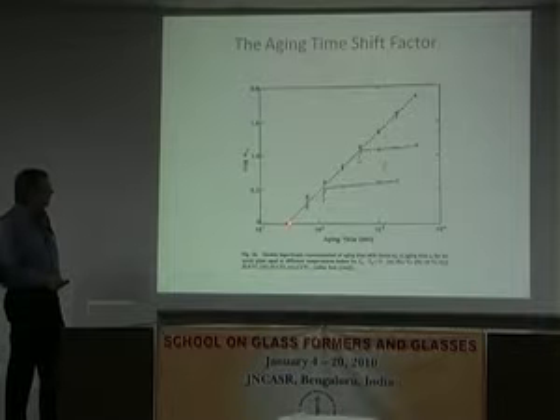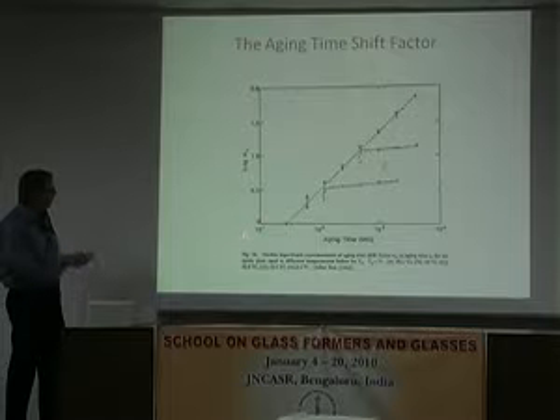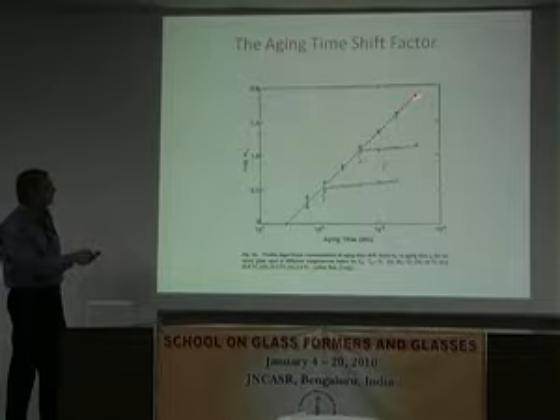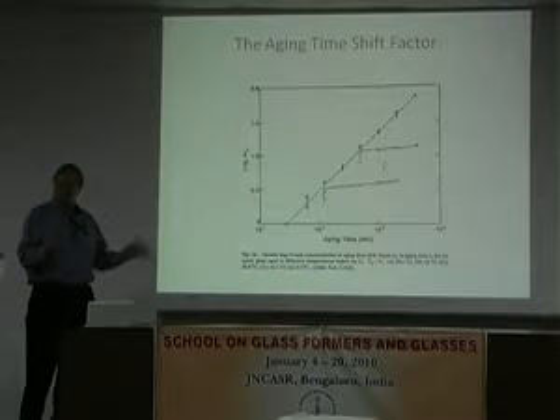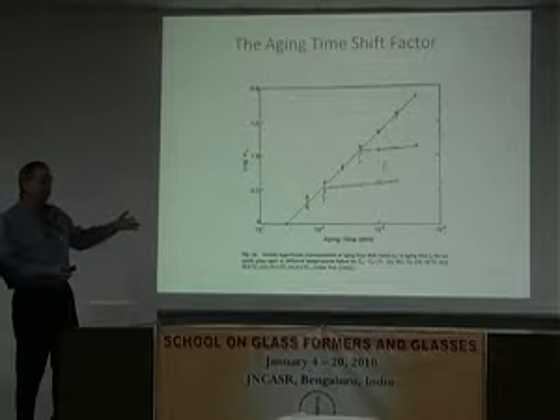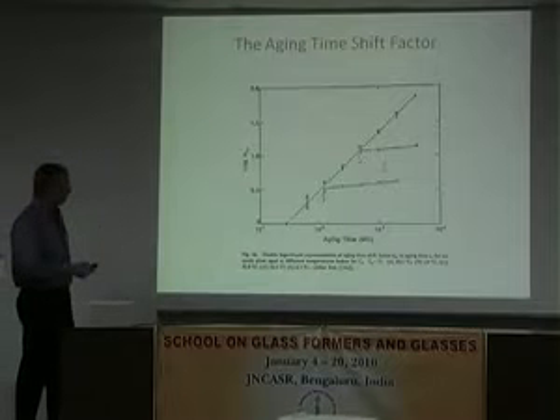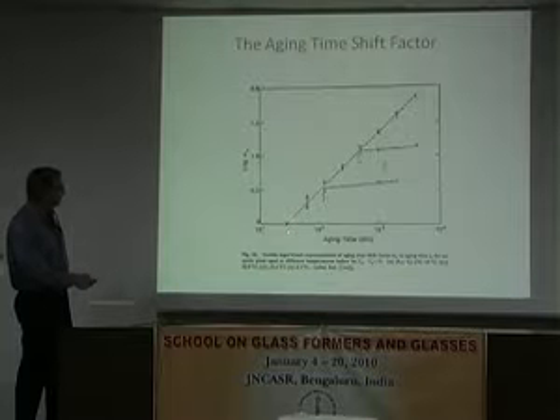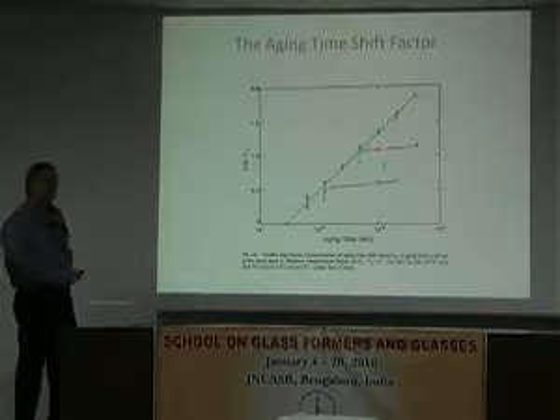So let's define the shift factor. This is some typical data. This is our data for an epoxy glass. And here's what happens in many cases: you'll find your shifting goes like a power law. When I plot the log of the aging time shift factor versus log of the aging time, I'll find myself in a power law regime. I'm going to come back to this in a minute. He found that the slope varied depending on the polymer and the temperature. If you don't have any aging, it's 0 at the glass transition. When you go lower, it increases to some maximum value and then comes back down to a lower value. Very seldom was it ever 1, which a lot of people look for. The other thing you can see here is when I age at 5 degrees or 10 degrees below the glass transition, you can actually see it coming into equilibrium, just like the volume does, right? The volume comes into equilibrium, so you see that this is coming into equilibrium.